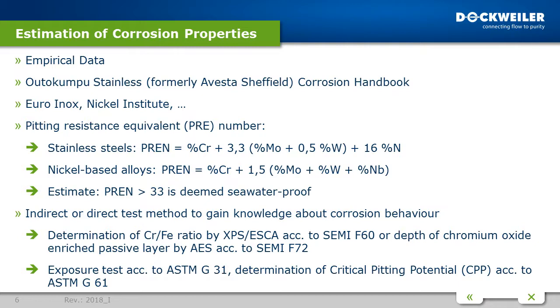In most cases of daily business we need something faster. One very fast method is to calculate the Pitting Resistance Equivalent Number (PRE). It is a measure of the relative pitting corrosion resistance of stainless steel in a chloride-containing environment. A common feature of newer steels is a high content of chromium, molybdenum, and in most cases nitrogen. The PRE is calculated as the weighted sum of the most important alloying elements; you only need the element concentrations from the 3.1 certificate. As a rule of thumb, everything above 33 is considered seawater-proof. For example, S31603 has a PRE number equal to or greater than 23.